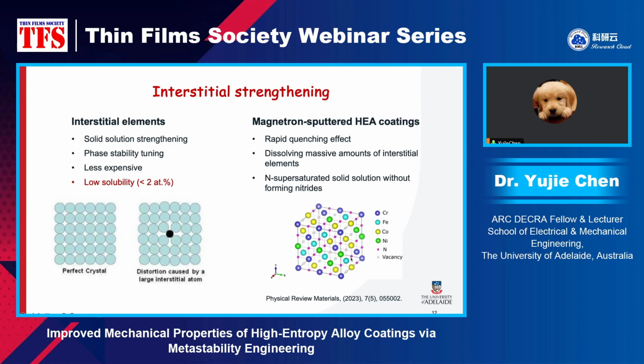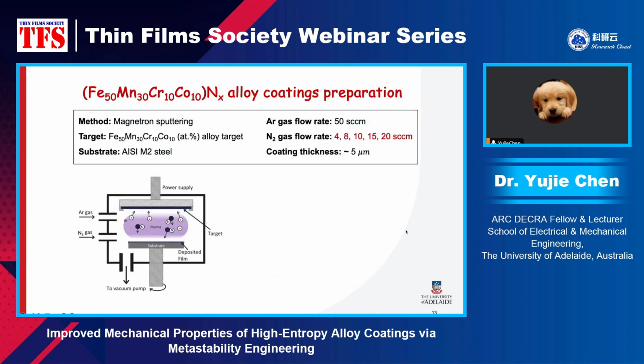This is what we would like to achieve: all these metal elements in the high entropy alloy are just randomly distributed. And this pink nitrogen atom just sits at the interstitial sites, randomly. They don't form nitride. Then we prepared 5 high entropy alloy coatings using this magnetron sputtering technique at different nitrogen gas flow rates. We set it at 4, 8, 10, 15, and 20 SCCM. And we know that different nitrogen gas flow rates will give us different nitrogen content in the coating.